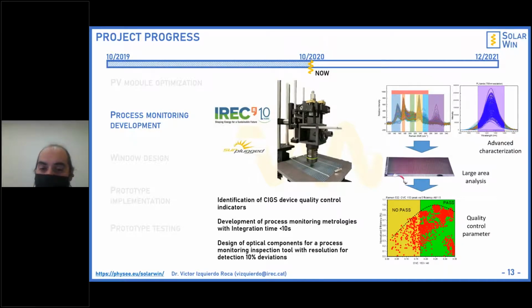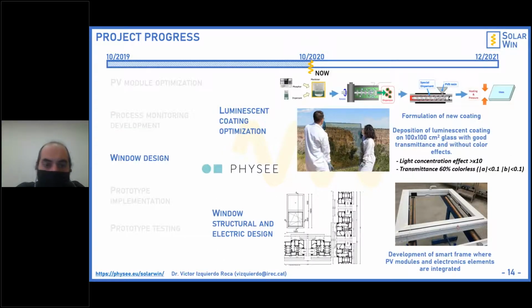It's required that we make inline process monitoring to follow the production of the devices on time. And this means that we need to generate mapping analysis in short times. Here we optimize the process monitoring tool to achieve measurements lower than 10 seconds and provide enough information for identifying what is the problem in the manufacturing of the panels.